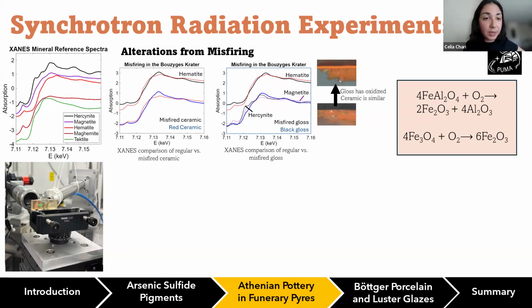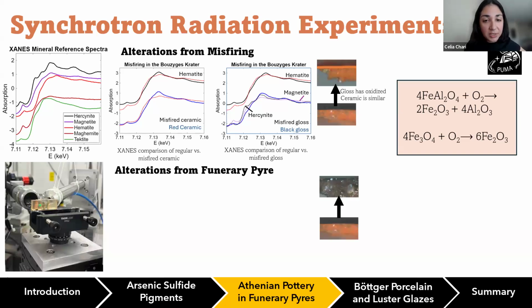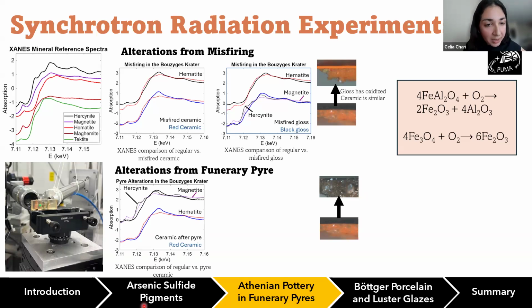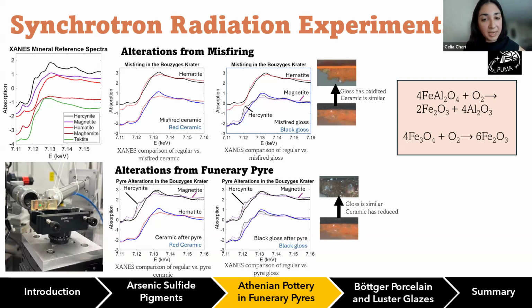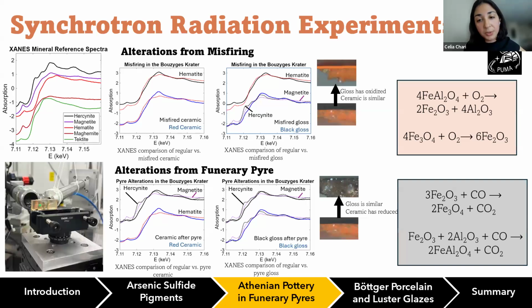and it's listed here. And as a second point, with the funerary pyre, this is where the ceramic substrate itself has reduced, but the black gloss appears to be the same. We see that the ceramic starts to contain signs of hercynite and magnetite. So this is confirming what we initially thought, that there is a reduction of the ceramic and that it is because of the creation of hercynite and magnetite, whereas the black gloss stays the same. So the gloss is similar, and in this case, the ceramic has reduced. And here are some proposed mechanisms of how that happened.